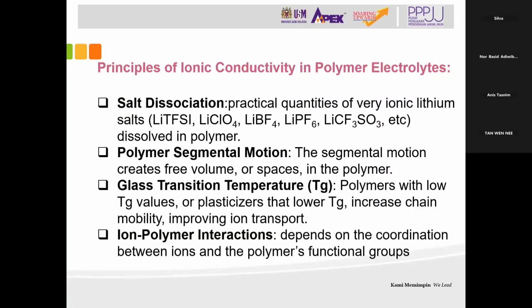For polymer segmental motion, in polymer electrolytes, ion transport is facilitated by the segmental motion of the polymer chains, especially in the amorphous, non-crystalline regions where the chains have greater flexibility. So the segmental motion creates free volume or spaces in the polymer through which ions can hop, and it will allow for ion transport.